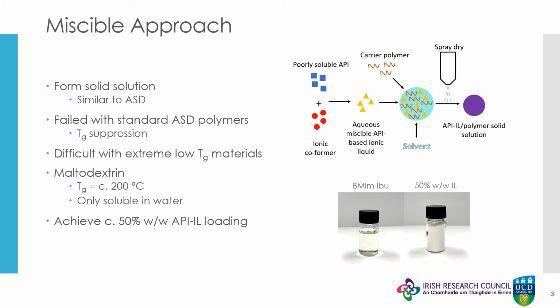The most obvious approach for solidifying IL drugs via a direct spray process is to combine it with the polymer carrier to create a single-phase solid solution, similar to what is achieved when producing amorphous solid dispersions of APIs. Using this method, we've been able to successfully solidify the IL by combining it with a polymer that has an unusually high glass transition temperature that offsets the extremely low melting point of the IL.